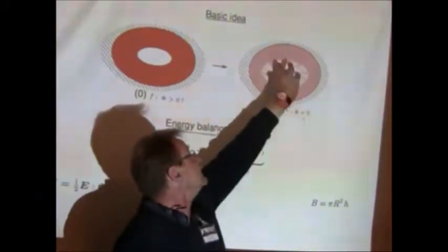This is a little bit tricky, because what we actually do is, you might remember that in the free energy density, for instance, we use the density of the material, which does not change. What we do is, we say this is due to microcrack evolution. For the load-bearing capacity, we just replace the genuine void, or the original void, by a bigger one. But this doesn't alter the density of the material, because we have only microcracks. But if you're talking about how stress is related to strain, then in terms of damage evolution, we express it as, okay, the void is now bigger. If you have another material, or let's say another damage mechanism, this philosophy will change. This we applied only because we had porous, elastic materials in mind.